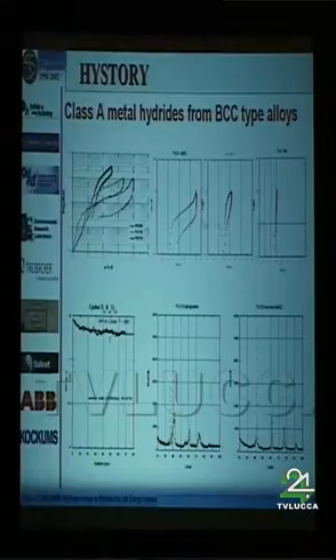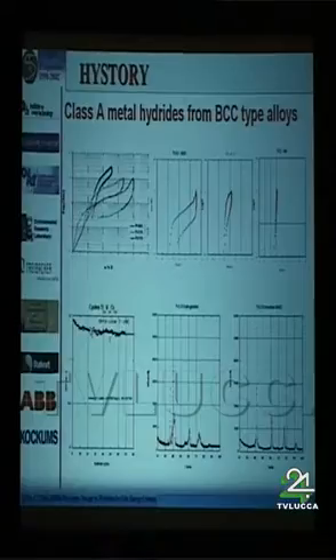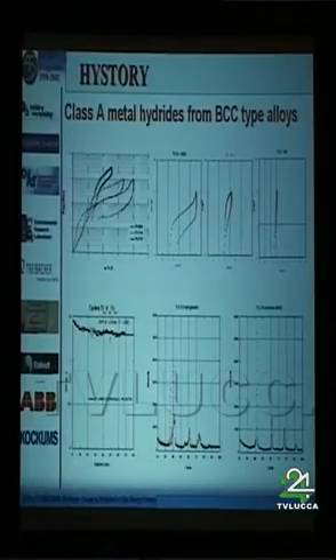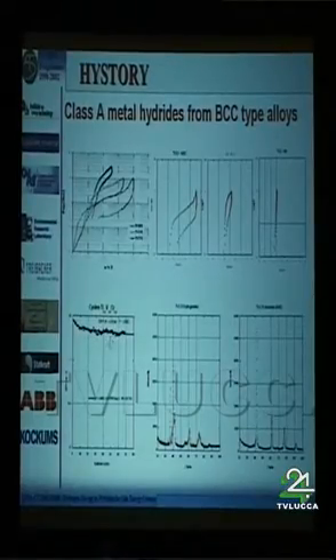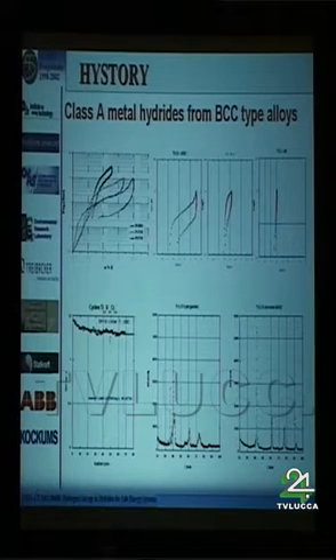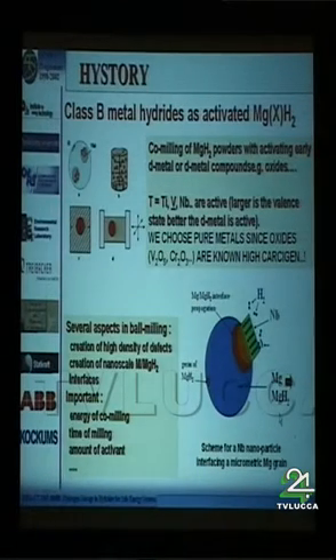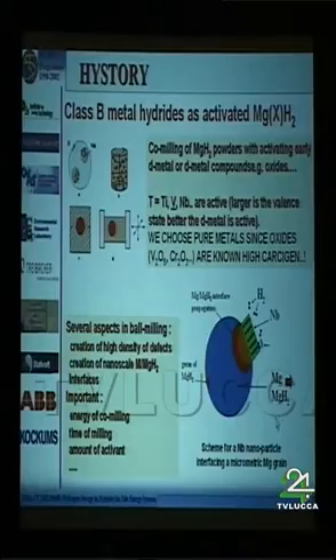This is the best achievement we got, and so we have a look about the stability, because the BCC are known also to be, for certain case of formula, rather unstable. So we have started to analyze the stability with the cycling of this type of metal hydride, and it appears particularly stable.